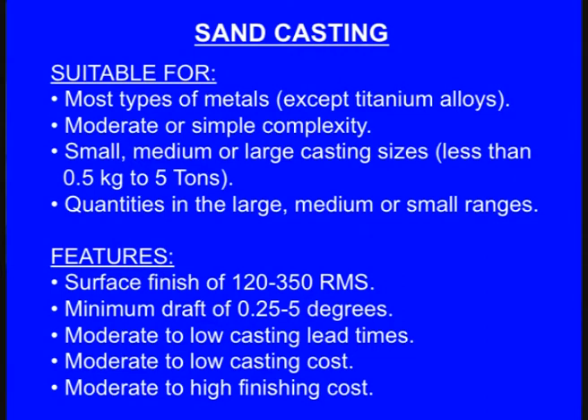Sand casting requires a draft of 0.25 to 5 degrees so that the pattern can be withdrawn from the mould. Casting lead times are moderate to low, and casting cost is moderate to low. Finishing cost is moderate to high, because we get a rough surface finish and need to machine it.